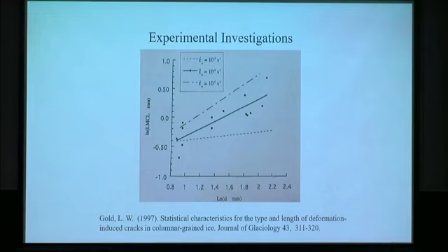So that means that with a larger grain size, you're going to get larger cracks. And if you look at the rate of loading, it seems that the higher the loading, for example, from 10 to minus 5 to 10 to minus 3 per second, you tend to get smaller sizes for these crack lengths. So all these were experimental reports or observations.